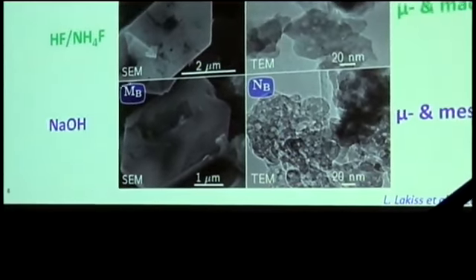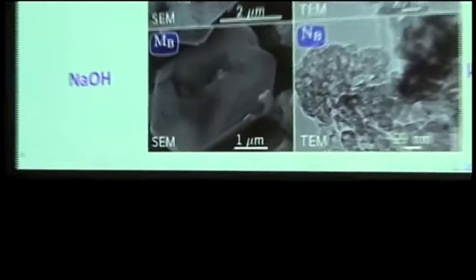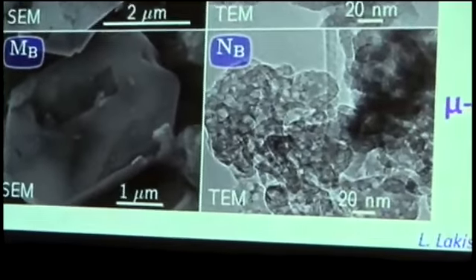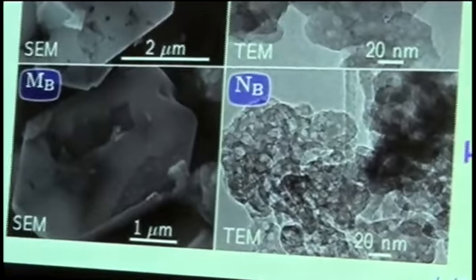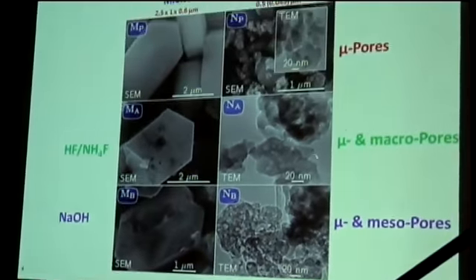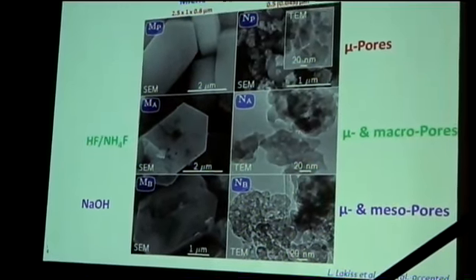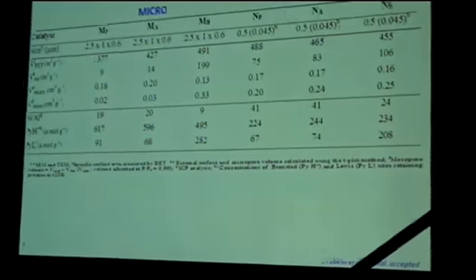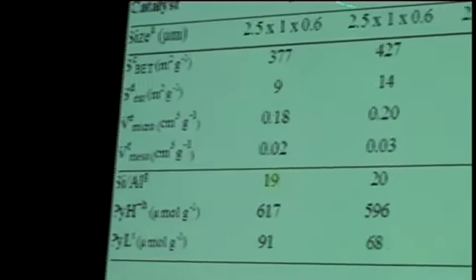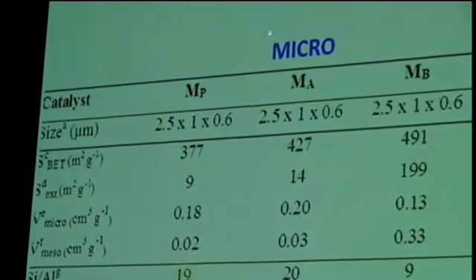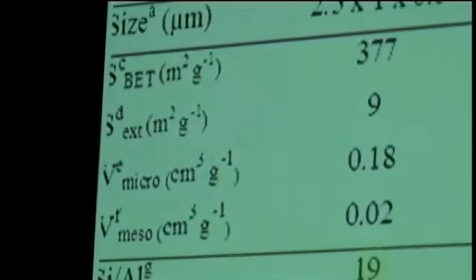And then the last one is the caustic treatment that I refer to as MB, against MA for acid, MB for base here. We did that on the micron-sized crystal, and each treatment we repeated on the nano-sized zeolite. So we have three types of catalysts containing micropores, micro plus macropores, micro and mesopores. If we look at these materials, we see first that the sample received from Süd-Chemie, so the micron-sized crystal, has a silicon to aluminum ratio of 19, while the material here, the nano, has a silicon to aluminum ratio of 41.